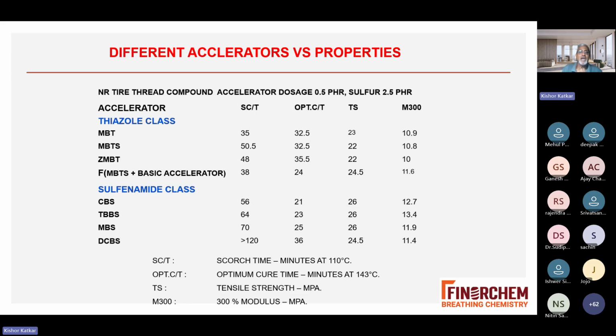Now you can see MBT scorch time is 35 with 0.5 phr. If you go from MBT to MBTS, your scorch safety is increasing to 50.5. Same dosage, but you can change it. So now a rubber compounder can understand, if you want to increase the scorch safety, what to do. Now come to the sulfenamides. CBS gives 56, which is higher than the thiazole. You go to TBBS, it is 64. You go to MBS, it is 70, and DCBS more than 120. So by changing the different accelerators, you can increase the scorch safety.